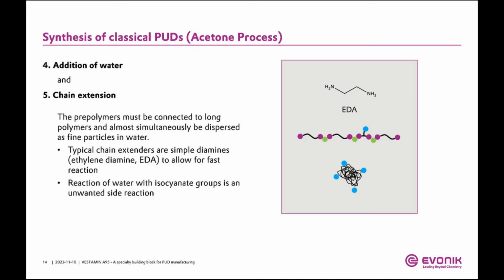The reason of this competition, that the water attacks your isocyanates and the isocyanates are then decomposed, is the reason that we usually use diamines as chain extender, because diamines react very, very fast with isocyanates, much faster than water would do, and also much faster than another diol would do. So that's the reason why we take advantage of simple diamines that are very, very reactive towards isocyanate groups.